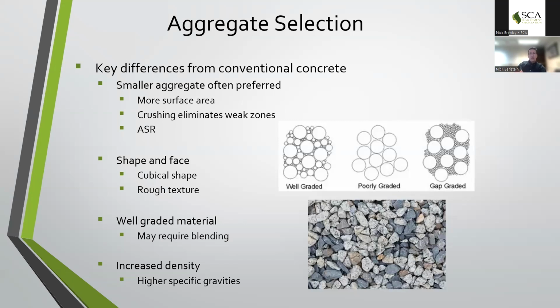Density of the material is also something that we strongly encourage be at least monitored. Most quarries have to provide some level of consistency in the density of the material they provide. However, higher specific gravities are often a good indication of a dense product, which is likely going to provide better overall performance if that is possible. So if you see your densities moving down or shifting greatly, it can play a major impact in the overall volumes you should have in your mix design for aggregate contents.